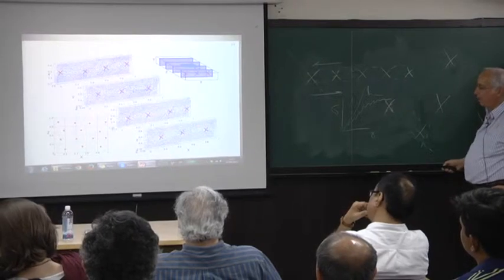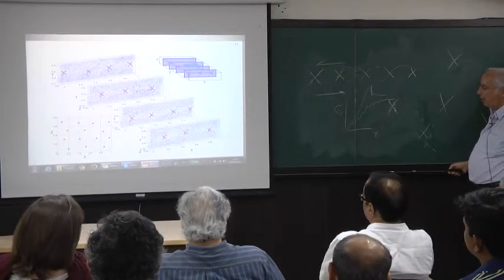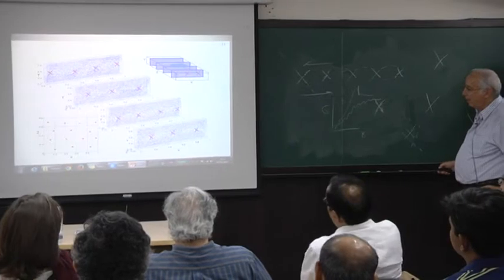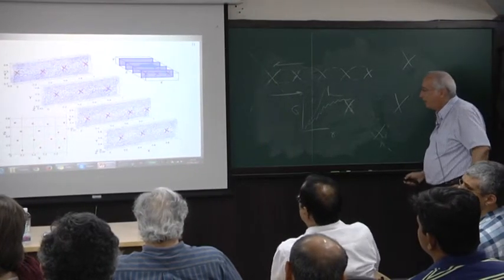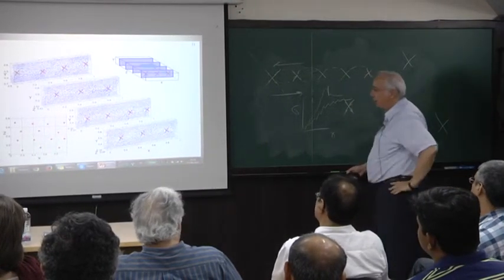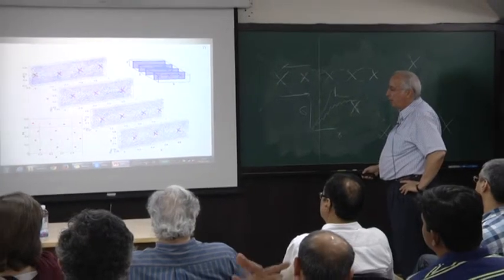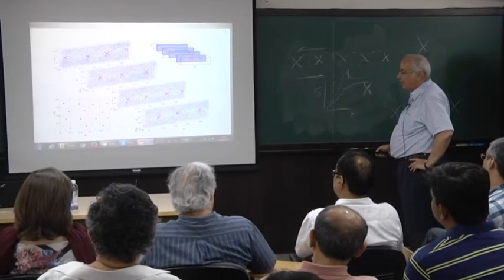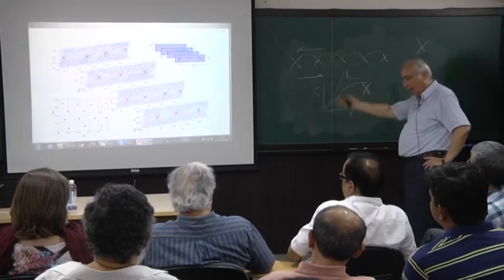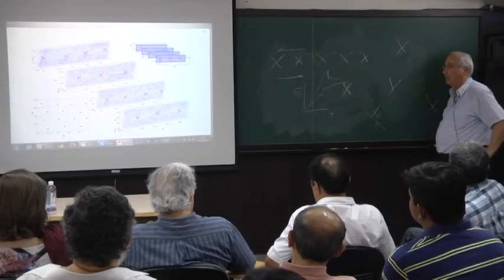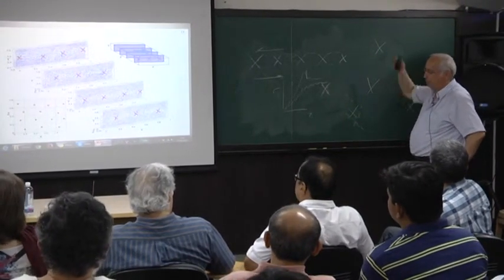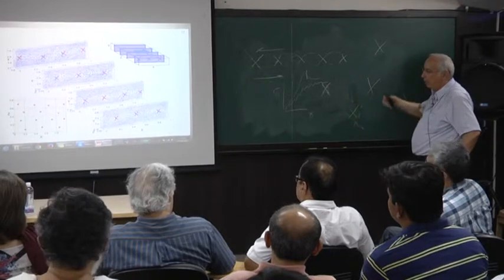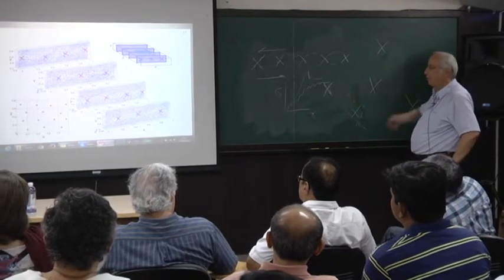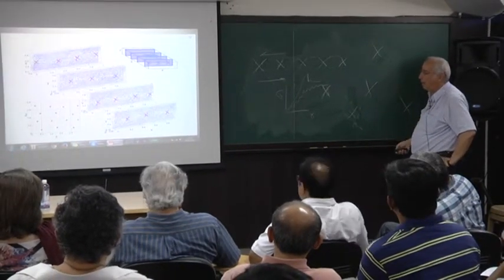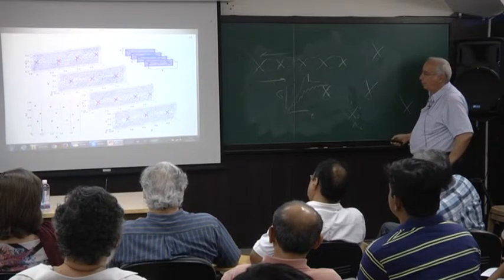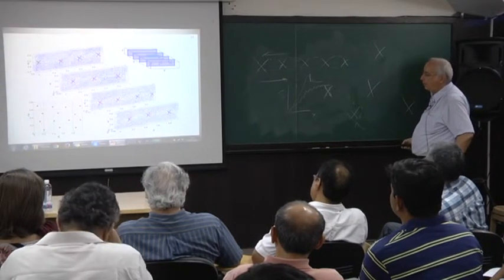This is now the numerical computation from numerical simulations, and it shows that the way that they are sitting when you look at this plane here is like this, on a triangular lattice. And this triangular lattice is predicted from the analytic calculation of the three-dimensional problem with all the Eshelbys in 3D, which is much more difficult, but still doable by hand, and the numerics seems to support the existence of such a thing.